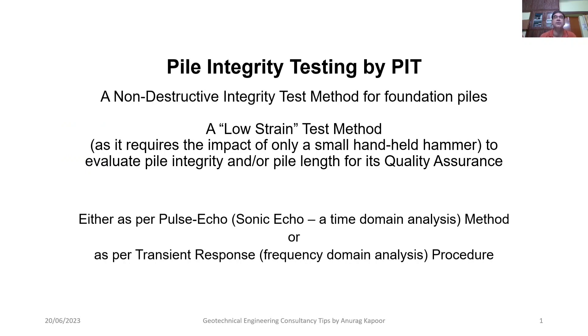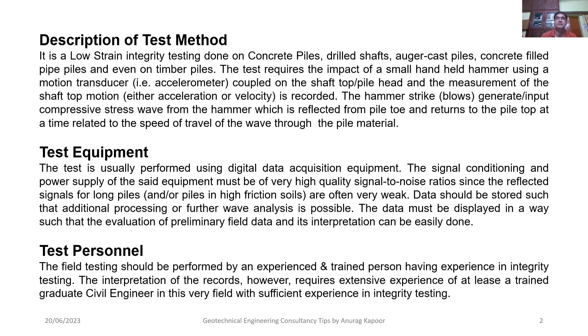Hello dear friends, welcome again to my YouTube channel Geotechnical Engineering Consultancy Tips. Today I will be telling you all about pile integrity testing by the PIT method, which is a non-destructive integrity test method for foundation piles. It is a low strain test method, requiring the impact of only a small handheld hammer to evaluate pile integrity and pile length for quality assurance. This is done by two methods: either pulse echo or sonic echo, a time domain analysis method, or the transient response frequency domain analysis procedure.